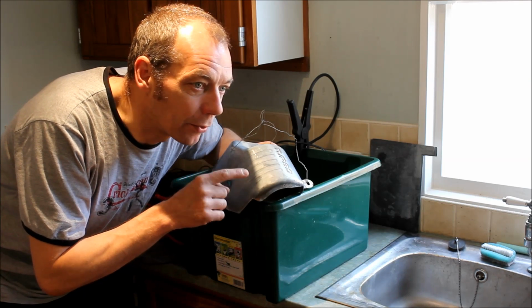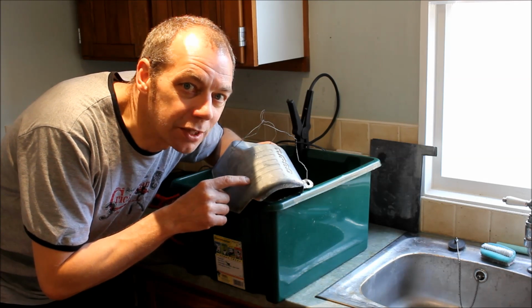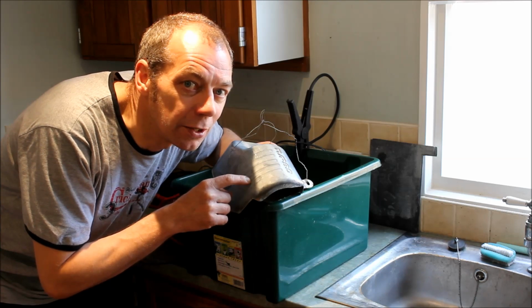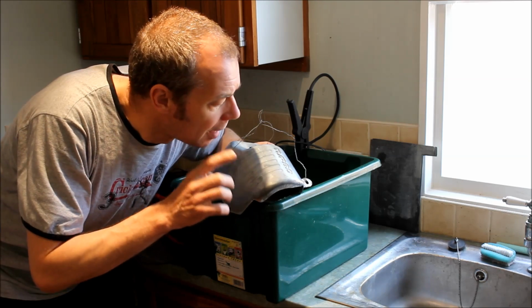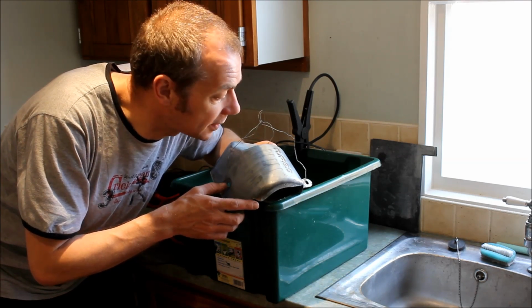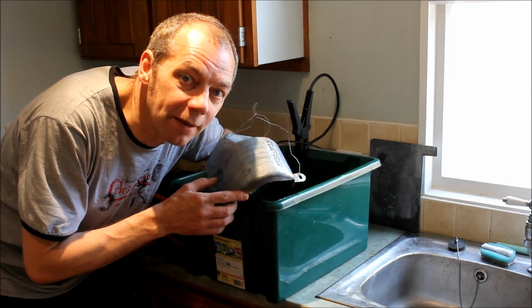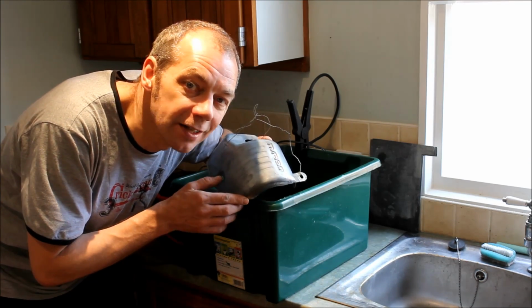Now, that's about 0.015 amps per square inch, which is about 1/7 of the current that you would normally use for an acid zinc plating bath. But anyway, I'm glad to say it's done now, so let's just get it polished up and then we're going to clear blue passivate it, get it back on the car and see how it looks.